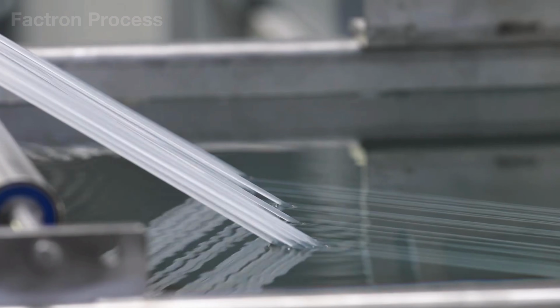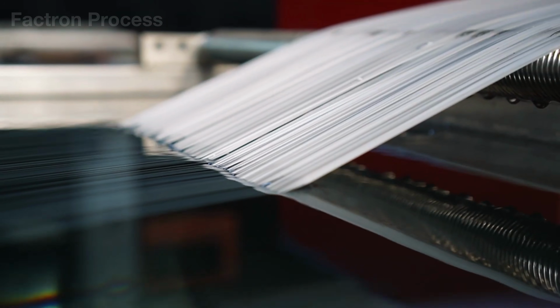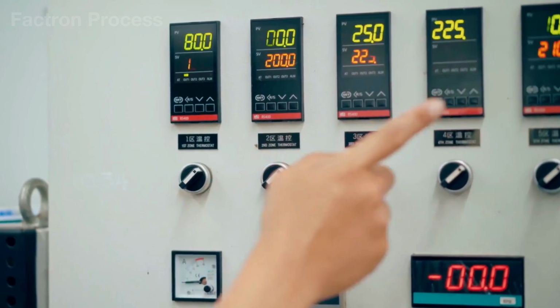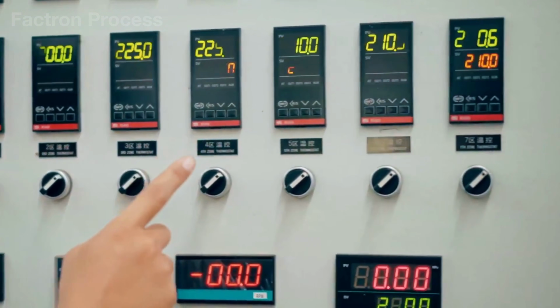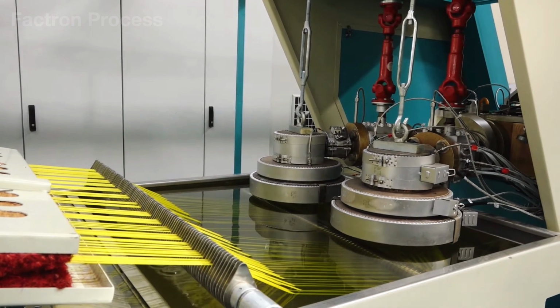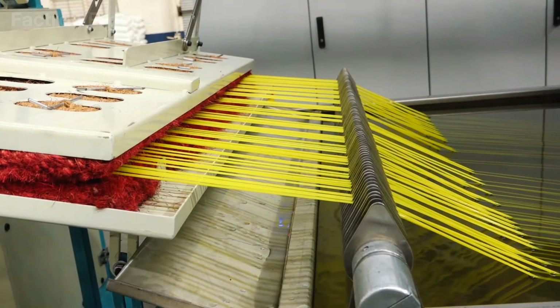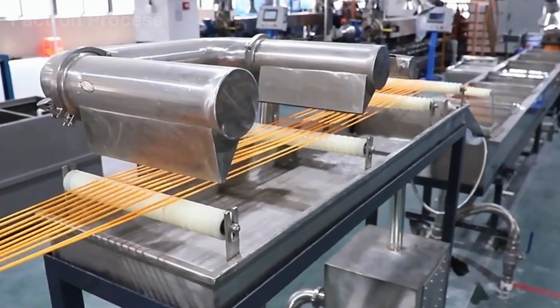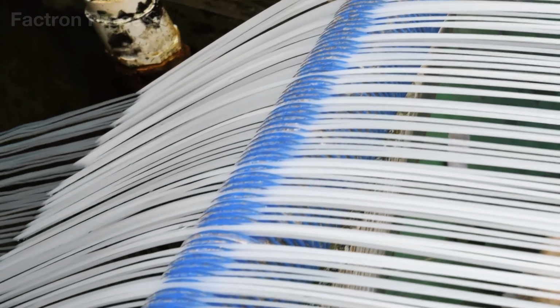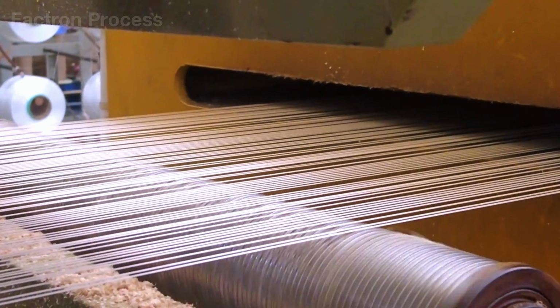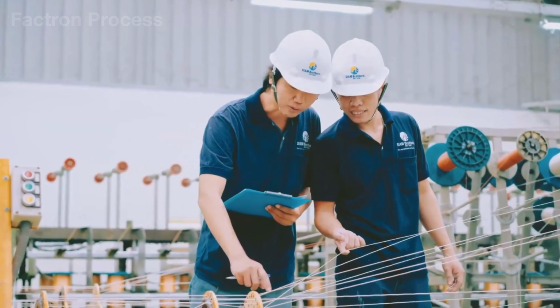As soon as they emerge from the spinneret, the filaments are still extremely soft and prone to deformation. They therefore pass immediately through a cooling water bath, typically maintained at around 68 to 95 degrees Fahrenheit, to rapidly reduce their temperature and lock in both the diameter and shape of each strand. Within just a few seconds, the hundreds of parallel filaments traveling along the production line have solidified, stabilized, and are ready for the stretching stage to increase their strength.